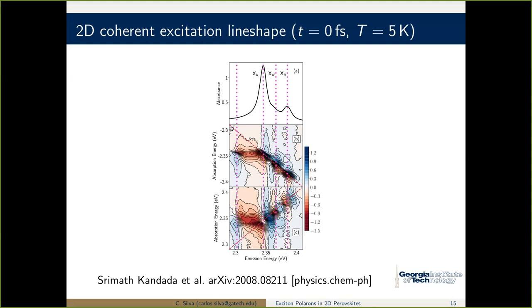The imaginary part is a dispersive spectrum. But here, when I show you the real part of these spectra, in fact, it looks like I don't know how to do a Fourier transform because it looks dispersive. And that's true for these two conditions of the experiment, where we measure the same thing. Here's our biexciton, our excitons. It looks like a derivative thing around the center. So it looks like a dispersive spectrum.